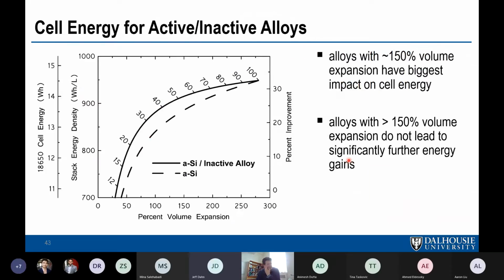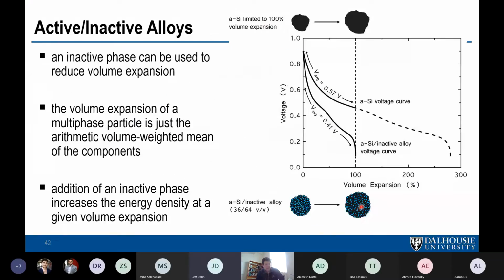One interesting thing when you make these active and inactive alloys like this, the silicon is black here. By the way, a lot of times you see the active and inactive alloys drawn, I think even in this presentation, in the opposite sense, where the silicon are dots surrounded by an inactive matrix. But that can't be, because otherwise the lithium wouldn't be able to get to the silicon. It has to look like this. The silicon has to be a percolating phase for the lithium to get to the core. So you have a silicon matrix with inactive alloy in it.